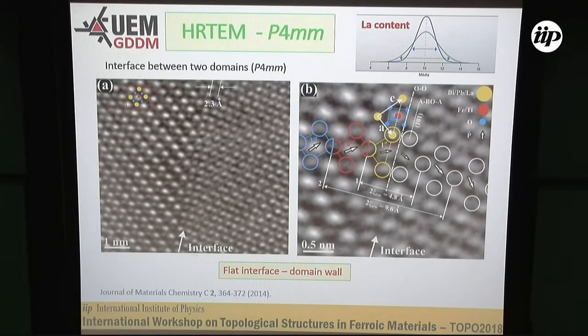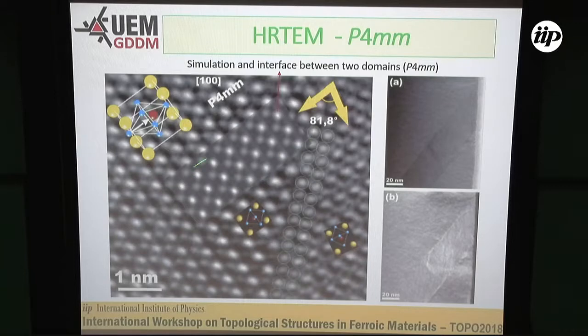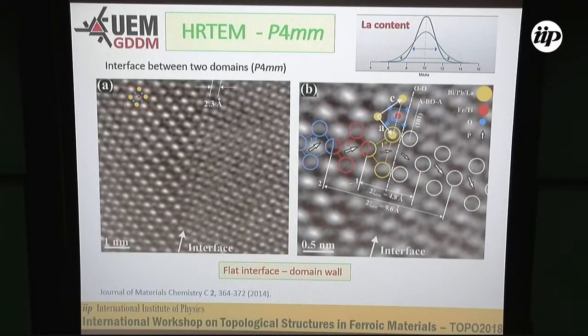And you see this interface, and you measure with the software 2.3 angstrom. And you can reconstruct this interface by using the information of our simulation, the simulated image, to reconstruct the domain wall or the interface in this case. If you consider that the arrangement is good here, this interface has just this distance. Your atomic arrangement is regular until here. This interface has about 5 angstrom.